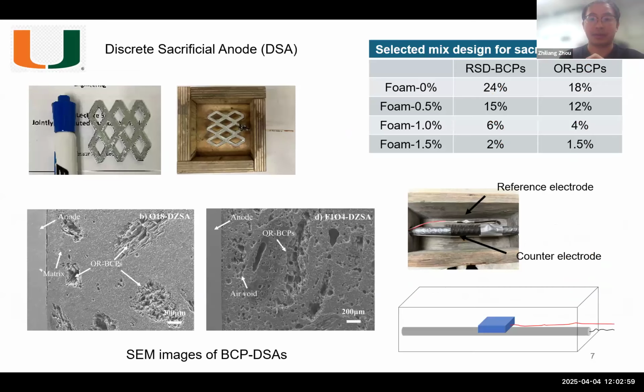And second, we selected several mixed designs for preparing sacrificial anodes. As illustrated in these pictures, the sacrificial anode is made of zinc that is embedded into the paste blocks. And the SEM images show the interface between the sacrificial anodes and the outside matrix that is porous. And third, the prepared sacrificial anodes were embedded into the reinforced mortars for rebar protection, and the corrosion condition with steel rebars is measured over time.